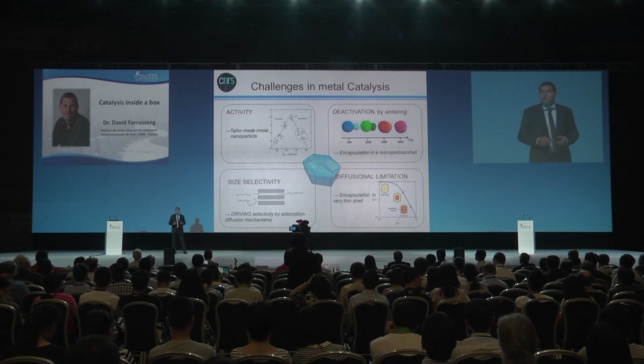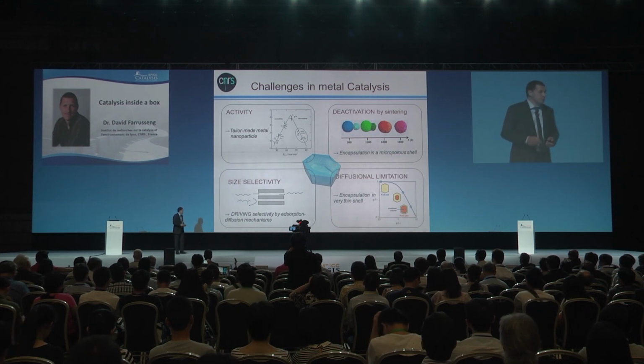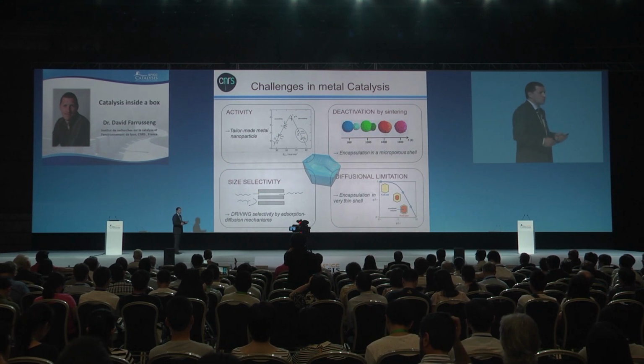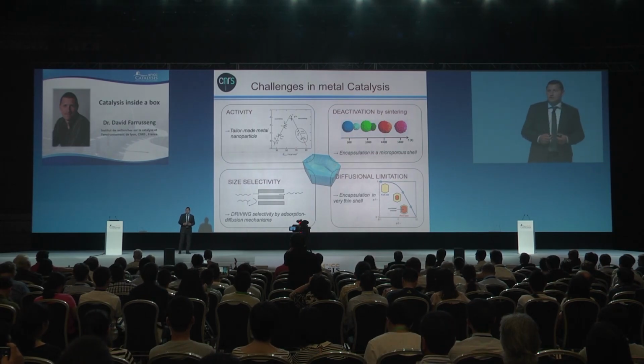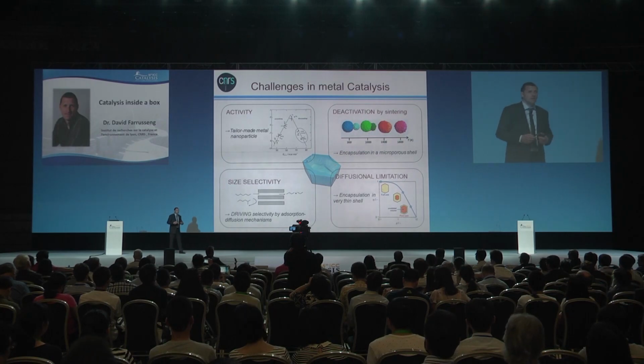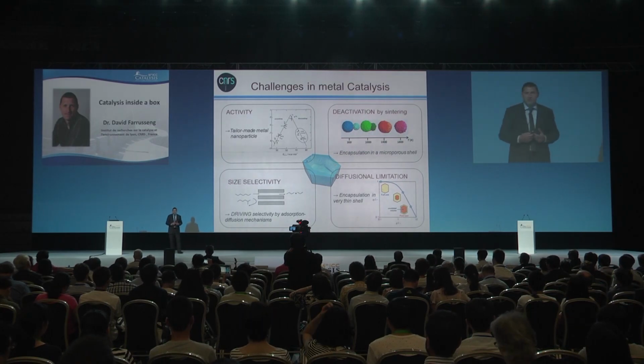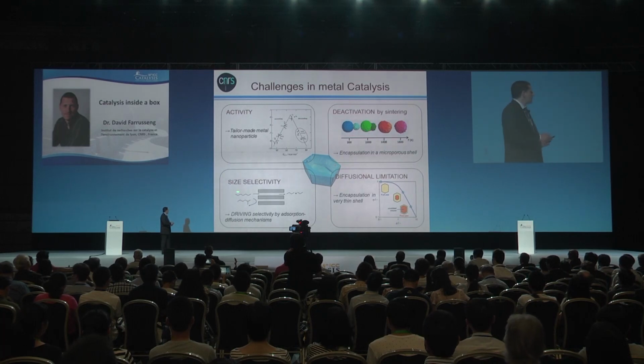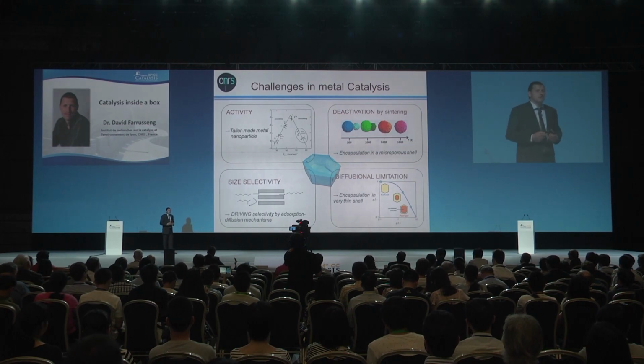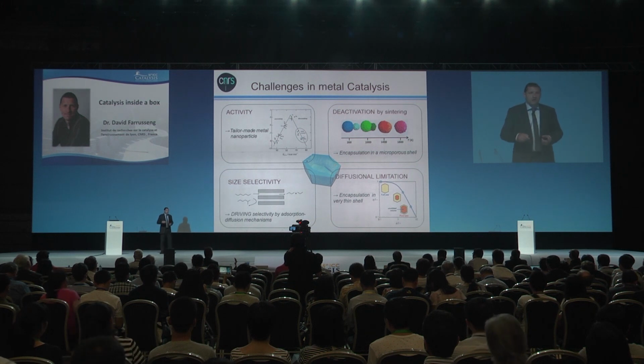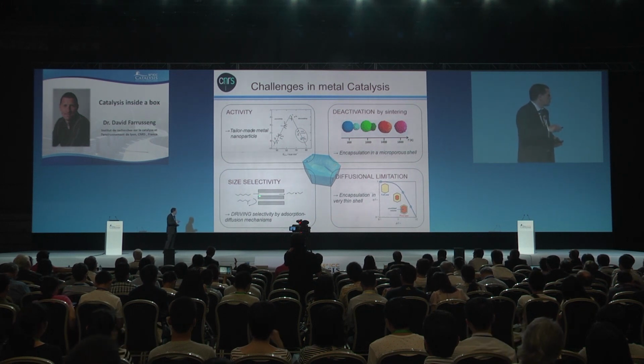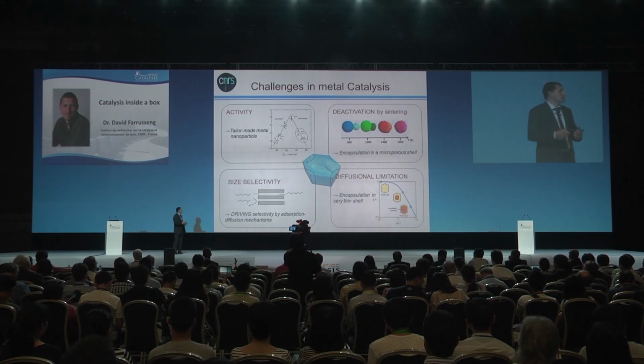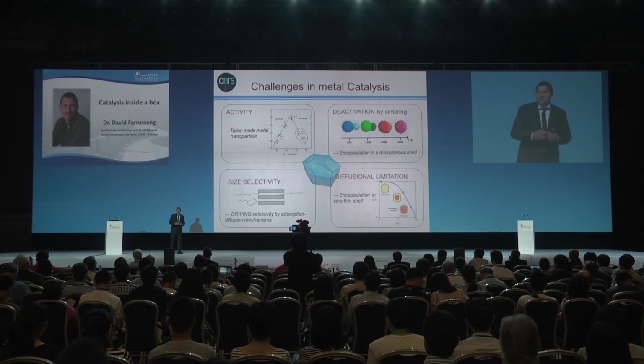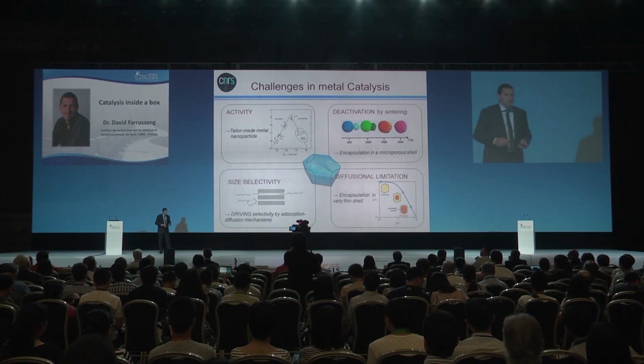Then I will move to the size selectivity. Size selectivity is very well known in zeolite catalysis. Because of the size of the pores, you can discriminate reactants of different size. This is not the case in metal catalysis, where all the reactants get access to the metal surfaces. So I will show you with 3 examples how we can, let's say, add a size selectivity function in metal catalysis. And briefly, I will mention diffusional limitation, because as you know, the diffusion of substrates in the pores of zeolites is very slow, and it may turn out that the activity that you measure is not the activity of the metal, but the rate of diffusion of the reactants in the zeolites.